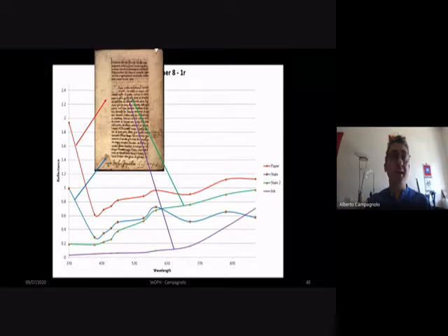What's interesting is that if you have enough wavelengths, you get a resolution that's high enough that allows you to recognize materials and pigments, even though you don't have it all on the same page. So you can identify materials according to their spectral curves through libraries of spectral curves. For this to happen, you need to have a given number of spectral curves through multispectral imaging.